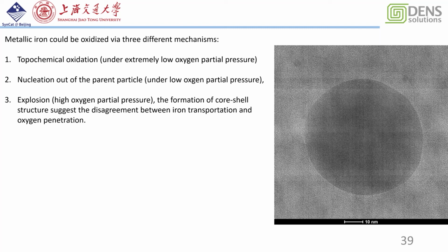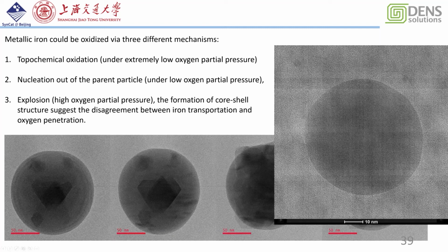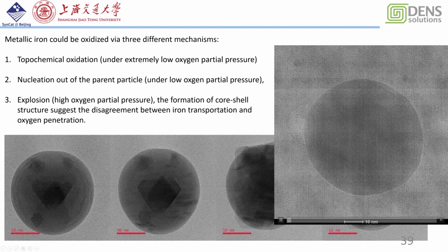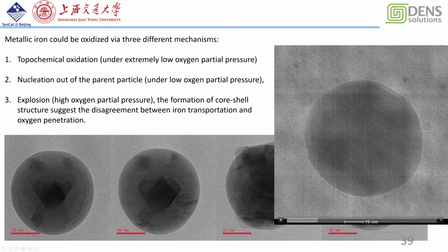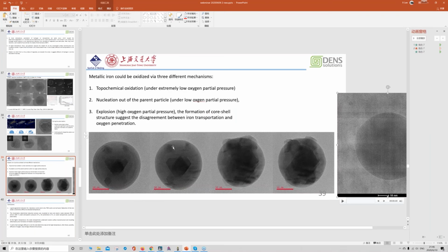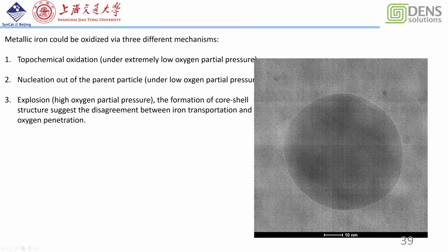So we also found quite an interesting thing: the oxidation of the iron is also determined by the pressure. At low pressure, we can see the formation of the iron oxide is a nucleation process. We can see gradual formation of the iron oxide on the surface of the iron particle. But with high pressure, it's very interesting. We can see definitely the reaction rate is very fast. But during the oxidation process, we found the core-shell structure. It suggests that the oxygen penetration or diffusion inside the bulk is very different.